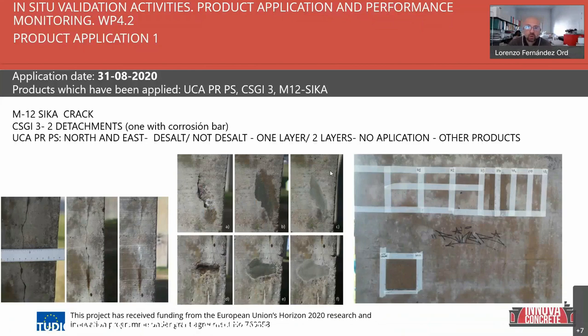We applied at Innovaconcrete basically three products, which are the M12 Sika, a mortar made by Torroja, which is the one you see in the second image here. Some two detachments, one in the top where you don't see the bar. The Sika is the one on the left. You see, we applied it in a crack. You see here the crack before applying the product, which is almost 1 to 2 millimeters. And we applied it inside this crack, and we monitor the performance of this mortar.